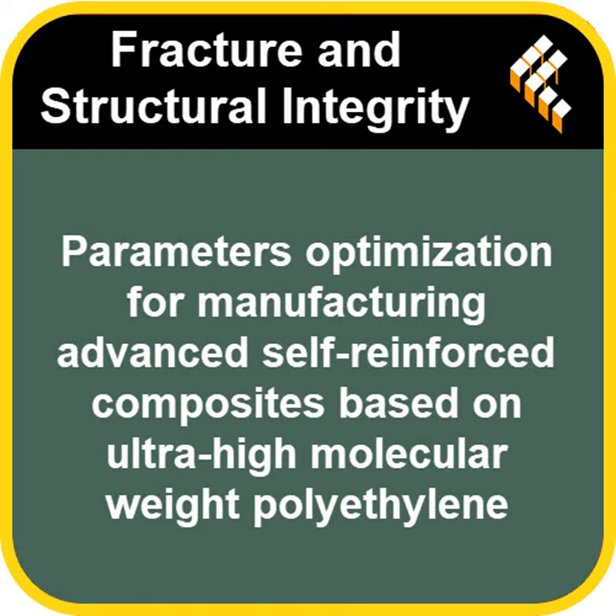The paper actually quantifies this. It measures the interfacial shear strength, basically how well the layers stick between UHMWPE fibers and a polyethylene matrix. And what did they find? An impressive 8.3 megapascals, MPa, which might not sound huge, but compared to putting UHMWPE fibers in a standard epoxy matrix, that only gets about 1.7 MPa. Wow, so more than 4 times stronger just by using the same family of material. Exactly. It shows how efficient this single polymer approach is. The material just bonds better with itself.